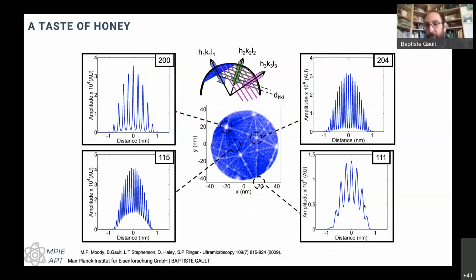And typically, if I do my reconstruction properly, it does match with what we would expect from the crystal that we know we have, in that case, pure aluminum. It's pretty simple. So we know we can do things not so badly. But as I told you before, the biggest issue is not in Z. The biggest issue is in XY. Laterally, some of these atoms are going to be repelled away from the center of the poles.